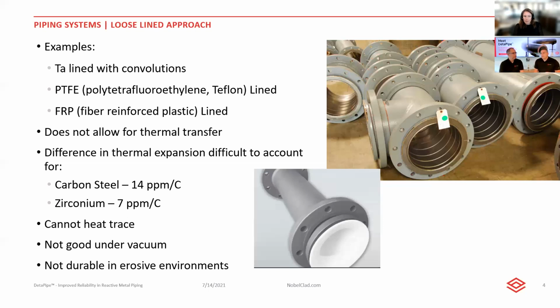Right. Because it's loose, there is air in between the cladding layer and the pressure boundary of the pipe. So things like heat tracing aren't really efficient or possible in some cases. Further, if you have to use them, not in vacuum, but at actual pressure and temperature, there can be differential coefficients of thermal expansion between the two metals, enough that when you weld the end of the liner to one end of the pipe to the other, you actually get the end of the pipe to crack, which is not good.